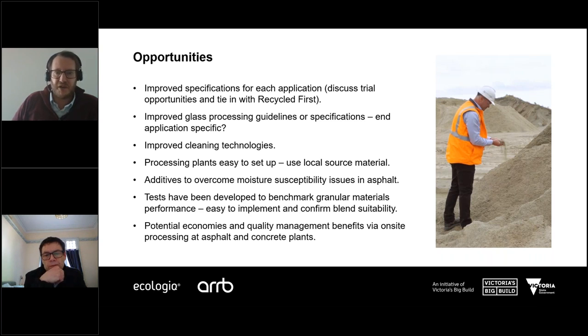So specifications are at the moment being further developed to give more advice and guidance. It's likely that these guidelines and specifications will be very end application specific. So again, as I mentioned before, if we were to be including glass as a drainage layer, typically we might be screening the product to 2 mil to 4.75 mil, that would be very useful for drainage products. Again, that's then giving an opportunity to have a finer size product, a 2 mil minus product that could potentially be more useful in wearing courses to prevent the potential for the larger glass sizes plucking out of wearing course surfaces.